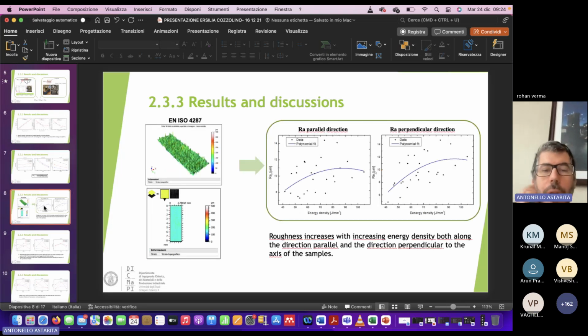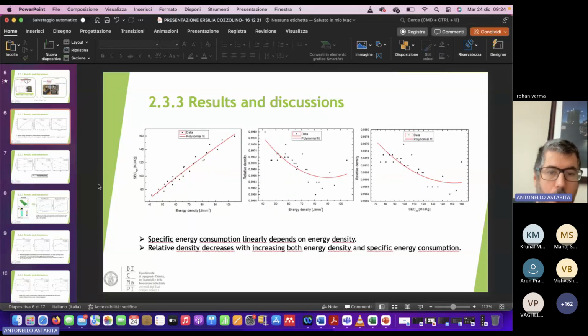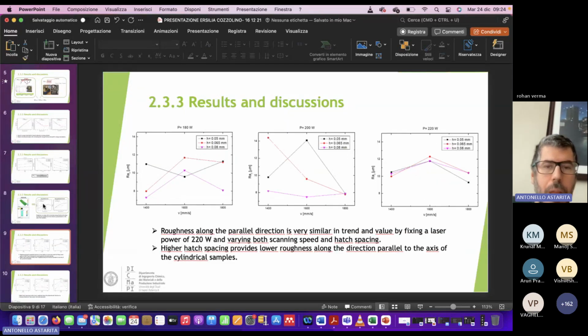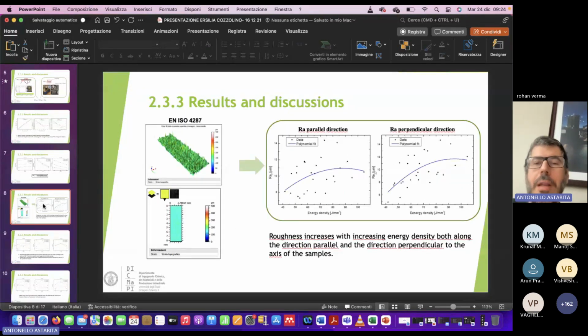Then we also measured the surface roughness to correlate the specific energy consumption to the roughness, because in the previous slides, we correlated the specific energy consumption to the density of the 3D printed parts. But as I said, when you perform post-building treatment, you also want to reduce as much as possible the surface roughness of the parts. Okay, so you need also to measure the roughness before and after the machining process.